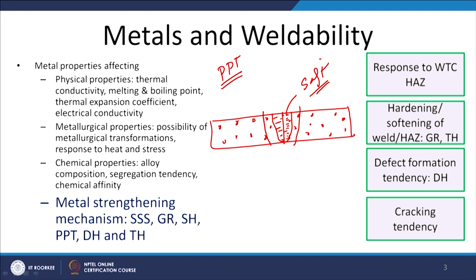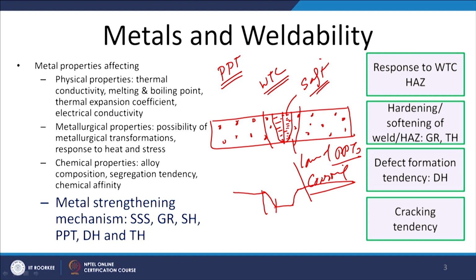Next to that, the heat affected zone which is being formed, there also due to the weld thermal cycle will have the loss of these precipitates, which is called reversion, as well as coarsening of the grains. So both these also reduce the hardness. So the weld will have the minimum hardness, then the HAZ will have somewhat greater hardness, and then the base metal, and a similar trend will be observed on both sides. So this is the zone where hardness reduction is taking place due to the loss of precipitates from the heat affected zone, and this is the zone where complete loss has been realized due to the fusion of the base metal, where reprecipitation of the precipitates was not possible, and that is why this leads to the formation of the minimum hardness zone.